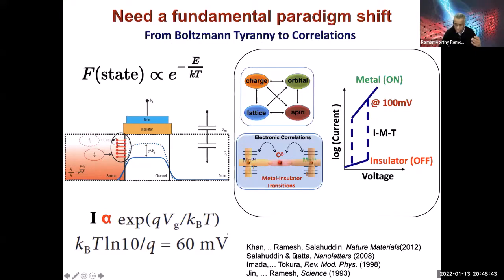The other pathway, which is something that many of us were involved in around the world. Yoshi Tokura, for example, he's done fantastic work. We were deep into colossal magnetoresistance. We indeed published one paper. We never pursued it. I thought that was not a good idea. You could start to think about using correlations or using these correlated systems where you have very strong interactions between the spin, charge, lattice, and the orbital degrees of freedom to create what you would call a metal insulator transition or an insulator metal transition, approximately the same idea, where you could get very sharp on-off kind of behavior. And this would look very much like an extreme case of a CMOS channel where you don't have an exponential dependence, but really a discontinuous dependence. But nobody has shown it at 100 millivolts. I'm going to get to the 100 millivolts in just about 5 minutes. Okay, so this is one pathway.